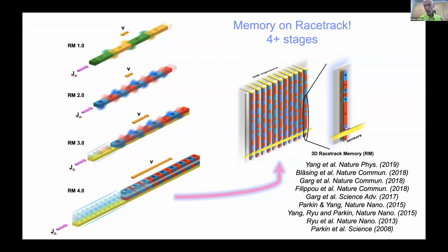In other words, the current passing through the material becomes spin polarized, and we could use that spin angular momentum to manipulate the domain walls. And as we demonstrated a decade ago, this gives you a maximum velocity of about 100 meters per second without burning up the wires.